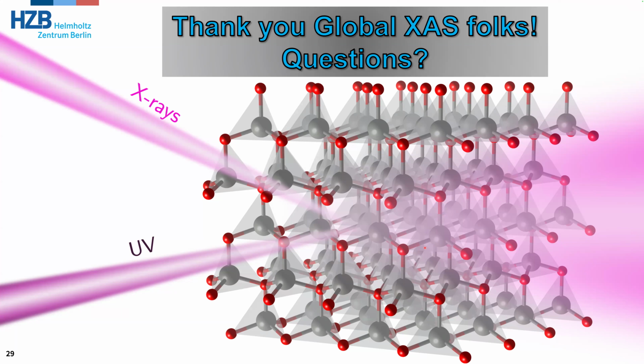Yeah, I'm just wondering, is there any evidence of seeing screening of core excitons by other core excitons, like in a steady state XAS experiment at extremely high X-ray fluences, or the core excitons just far too small for that to ever be possible? So this is a great question, and it's exactly what my first slides were talking about. I think now is a good time to look into the operando studies. So people basically shining just continuous light on materials, trying to capture differences in materials, and try to see if there is evidence of core exciton screening by also doing these measurements.